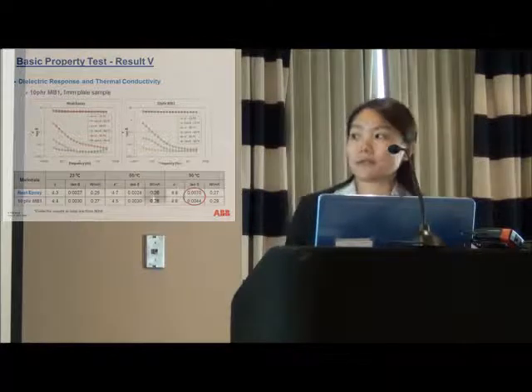But we noticed a very interesting thing here. At 90 degrees, the nanocomposite actually showed lower losses than the neat polymer, and it was not the same situation at room temperature. That's something very interesting, but we don't understand yet.